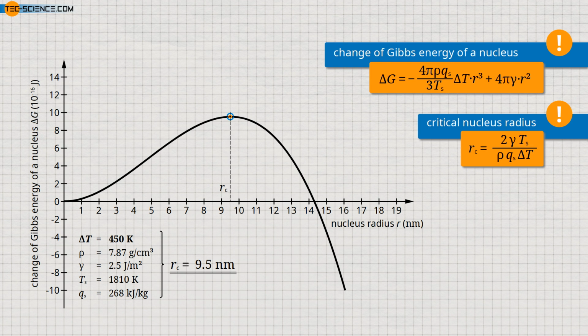As can be seen from the diagram for the change in Gibbs energy, energy must be supplied for nucleation in order to increase the Gibbs energy accordingly. This is done by thermal fluctuations in the melt, which can provide this amount of energy locally and for a short time. This amount of energy to be supplied is also referred to as activation energy for nucleation or free energy barrier. Only under the assumption that a randomly formed nucleus is so large that the change of Gibbs energy is negative from the start, crystallization occurs directly with release of energy.